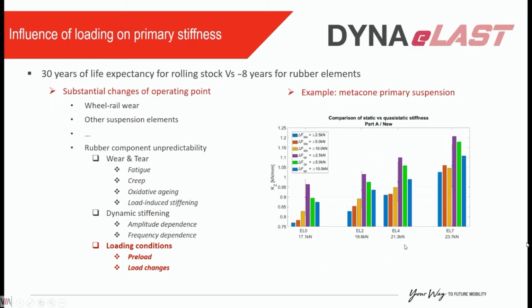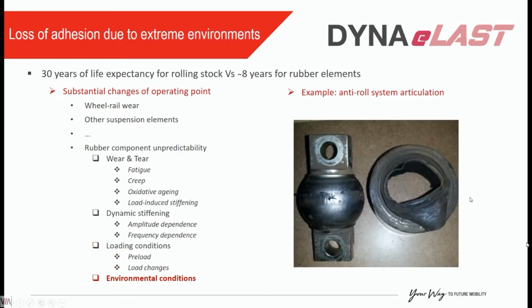If we look at some bar chart, what we see is how from AW0, as we increase the number of passengers, the stiffness increases a lot. From a safety point of view, the tare condition tends to be the most critical because it's the lowest load on the train, on the wheels, but because the stiffness increases so dramatically depending on the preload, this could become the most dangerous condition. And also I wanted to make a mention of environmental conditions.